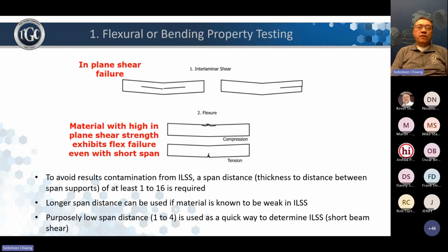If the test coupon upon failure looks like the pictures above, that is not a flex failure, that's an interlaminar shear failure. The material actually shifts between layers. A real flex, so that doesn't count. The reason why it doesn't count is because we do not have the adequate span distance. ASTM and ISO call for a 16:1 span distance. 16 is the distance between the two blocks, and then the 1 is the material thickness. If it's less than that, then you could run into ILSS failure.